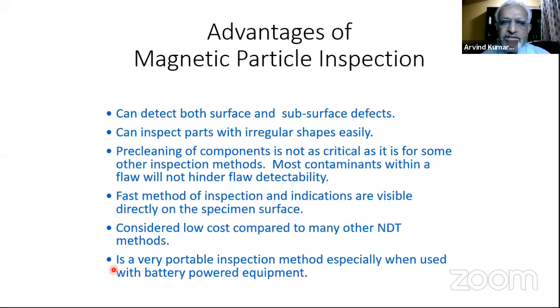What are the advantages? We can detect surface as well as subsurface defects, which may or may not be open to the surface, unlike PT. It can detect all types of defects irregular in shape, and pre-cleaning and this whole process is not very difficult to follow. It is a fast method for inspection, and indications are visible directly on the specimen which you are testing. It is very low cost compared to other methods like radiography and ultrasonic testing. It's a very portable inspection method, especially when used with battery powered equipment.